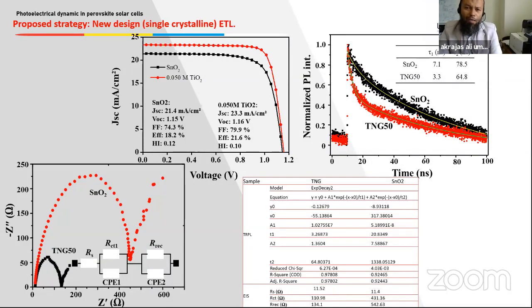but because the performance is high in nanograss, we can remark here that the charge transfer dynamic and transport dynamic in the device should be much more active. So the deficiency due to the recombination of the carrier can be compensated or overcome, so that high performance of the device can be realized.